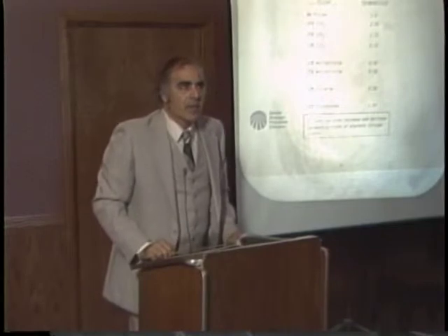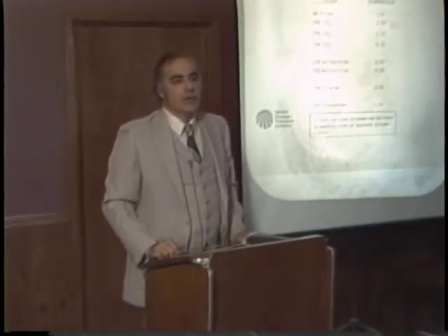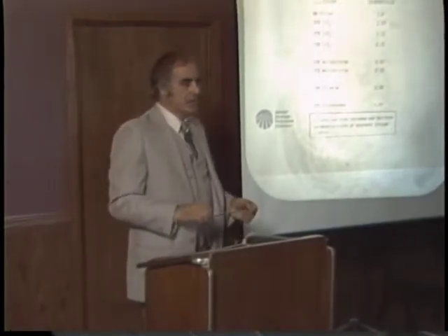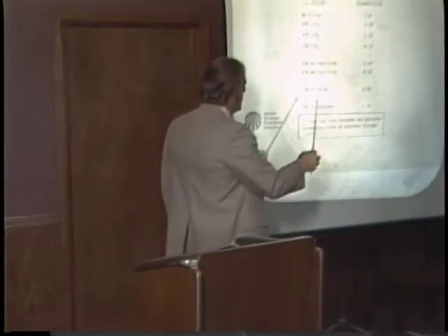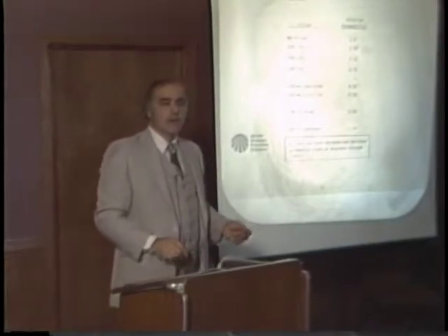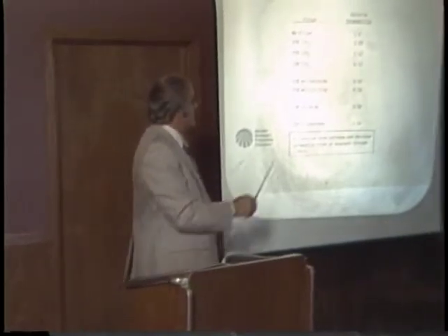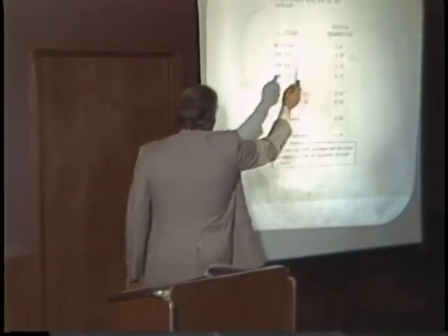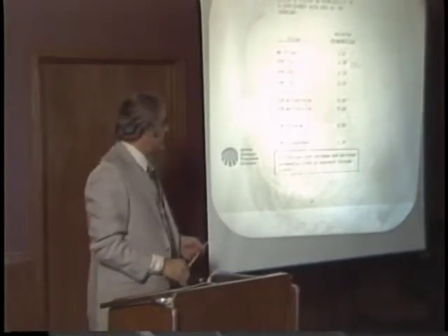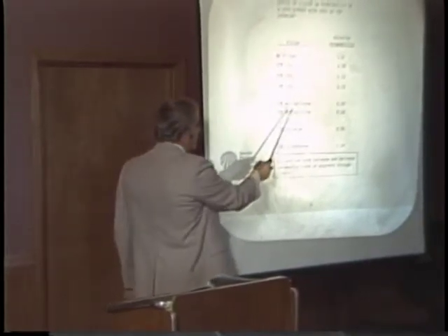We go to wollastonite, which is a replacement material for asbestos. It's a small fiber material, principally calcium silicate. And in this instance, we immediately retard the permeability of the migrant through that matrix at the same level where the permeability was increased by silica. So this turns out to be a very effective filler.